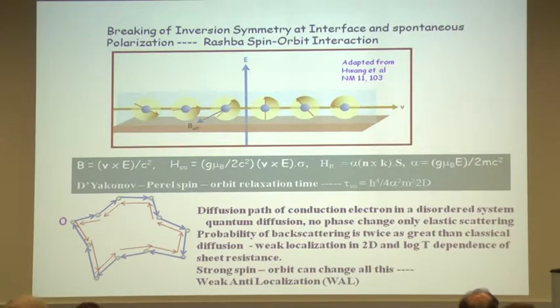Now, if you have strong spin-orbit interaction in the problem, then what happens is as this electron goes around the orbit, it can acquire an additional phase because now you are operating on the spin part of the wave function. And this constructive interference is sort of blocked. So what you see is the weak localization is stopped, and you go into a regime which is called weak anti-localization. So the resistivity will no more grow as a log of T at very low temperatures. It will become flat. It's one signature of weak anti-localization, which is coming because of the spin-orbit interaction.